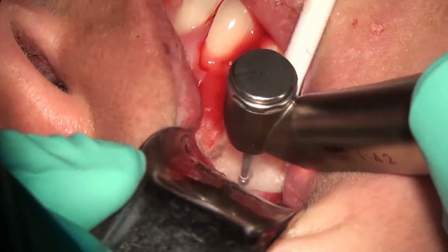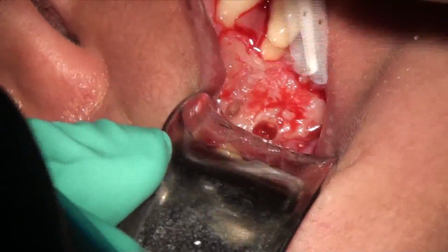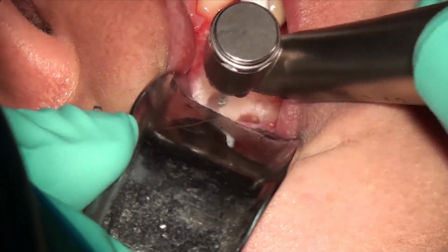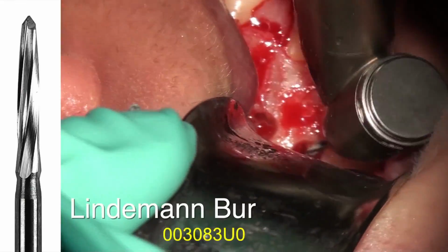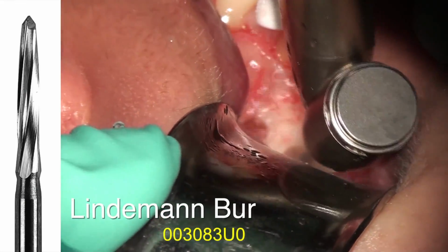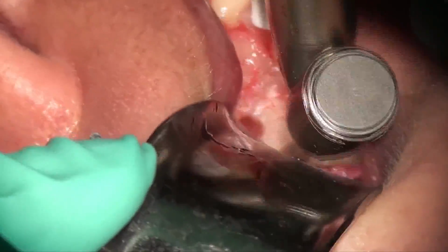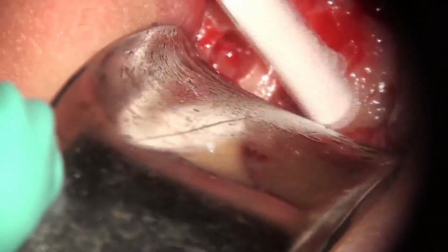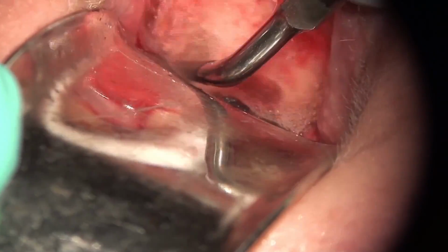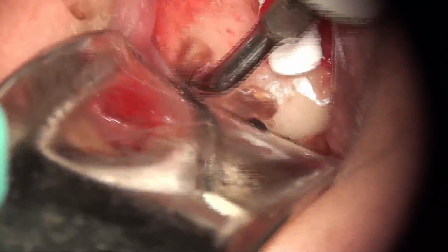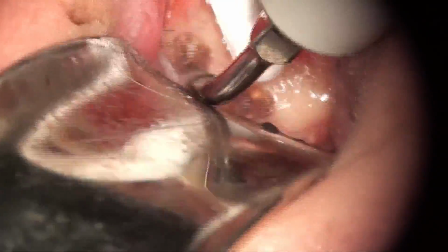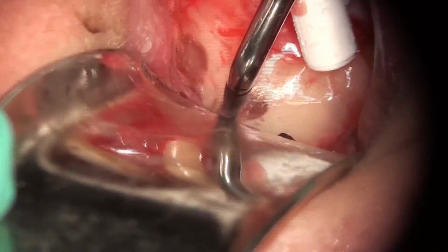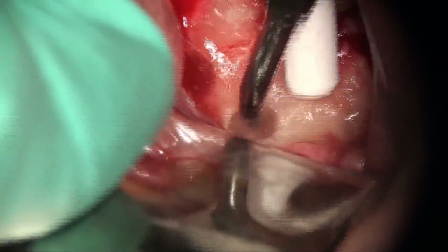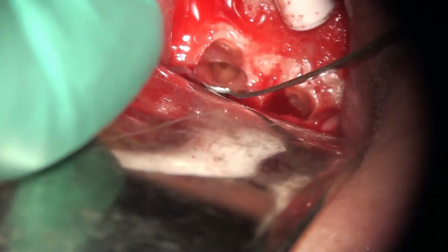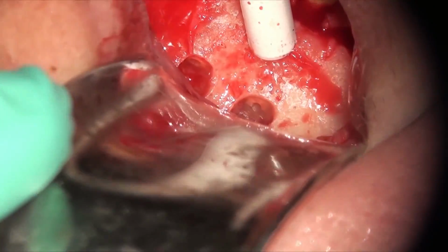and then we proceed to make our osteotomy. And the osteotomy is done using just a round burr with a very high torque electric handpiece. I'm using the Forza handpiece, which is an electric 45-degree angled handpiece, followed by the Lindemann burr to flatten the end of the roots. Once the end of the roots are flattened without any excessive bevel, then I'm able to use my ultrasonic tip. You can use whatever ultrasonic surgical tips you have. I use the BK1 and 2 tips by Brasseler, and then you just go 3 millimeters deep into the retropreparation, as you can see, and you have nice and clean retropreparations, and you check to make sure gutta percha